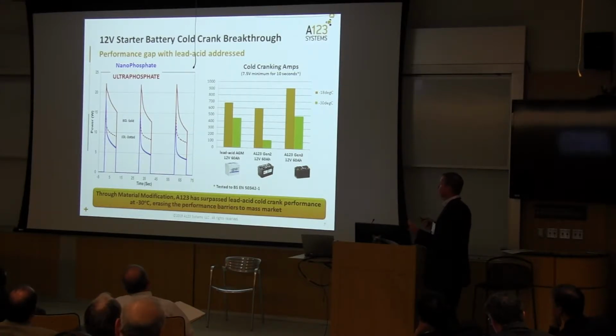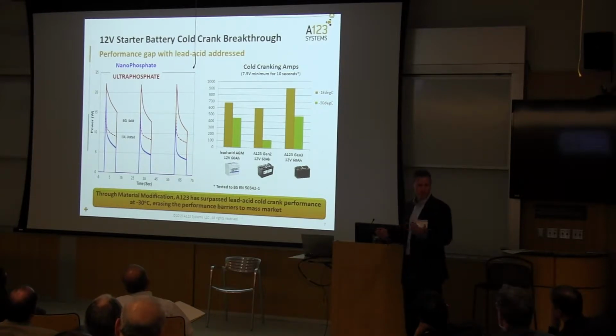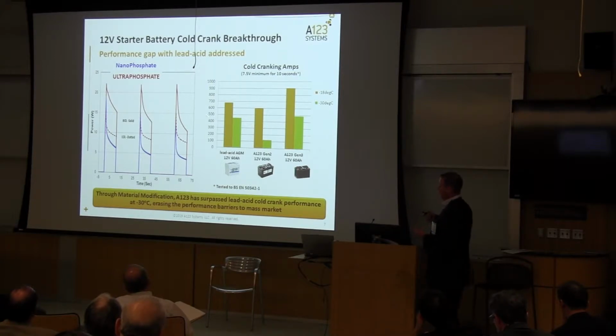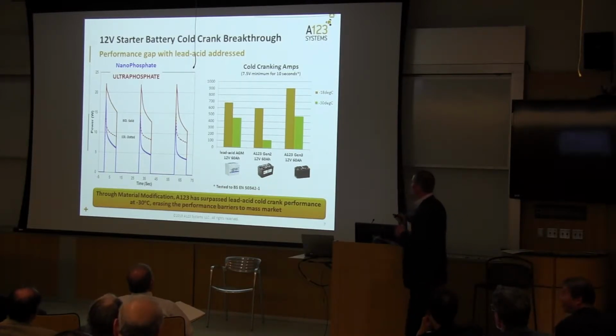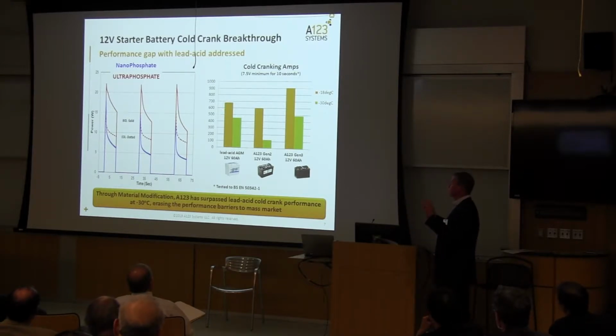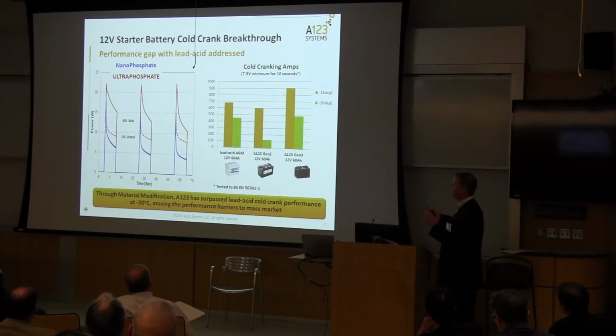So AGM not only had a cost benefit, right? It's only about $70 to $80 per kilowatt hour, but it also had a performance benefit. And that performance benefit is further increased when you go to about negative 30 degrees C, which, believe it or not, is required in certain parts of the world. The performance dramatically decreases. I was born and raised in Miami, so we never saw minus 30 C. So anyway, this was good, but again, really, it was the total cost of ownership that was driving some of these high-end vehicles. So we continue to push, and this is LFP advancements completely done internally at A123.